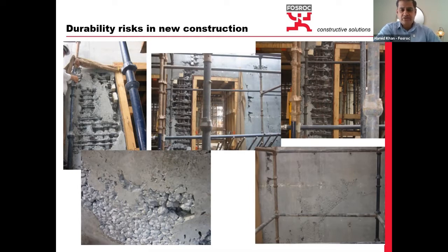So we say that concrete must not separate. The cement paste, water and aggregate must be together. If the aggregate and cement paste separate, this is segregation. If the water separates from the paste and the concrete, it's called slurry bleed or bleeding. As a result, we end up having honeycombing.